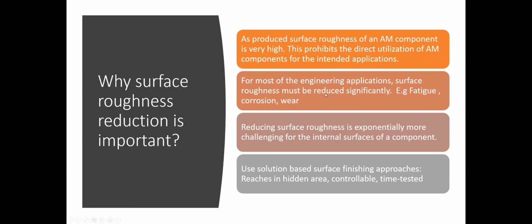The second reason is that for most engineering applications, surface roughness must be reduced significantly. For example, if somebody wants to apply metal 3D printed parts for aerospace or biomedical applications, you need to reduce the roughness, because when loading is of fatigue type, most defects start on the surface. Due to that, roughness reduction is very important. The same thing goes for corrosion and wear properties.